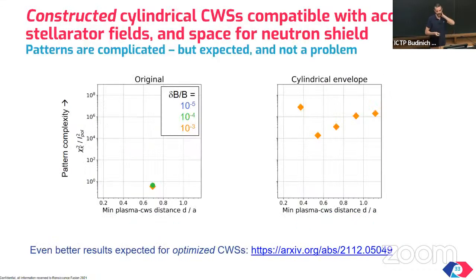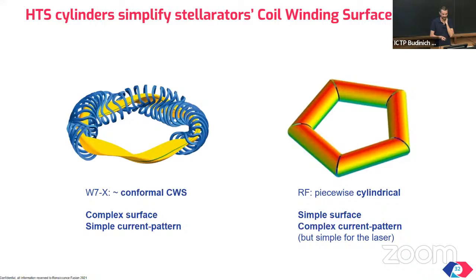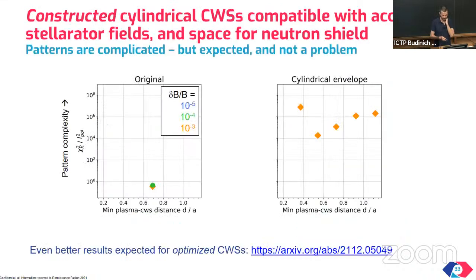And this is a proof that this is indeed true. So the plot on the left and the plot on the right correspond to the two configurations on the left and on the right of the previous slide. Shown on the vertical axis is a metric of coil complexity. Indeed, if you adopt a piecewise cylindrical envelope, you obtain higher values in this metric, a more complex pattern compared to adopting a conformal surface. But the important message here is that this level of magnetic field accuracy, 1 part in 10^3, is sufficient to build a satisfactory or more than satisfactory stellarator.